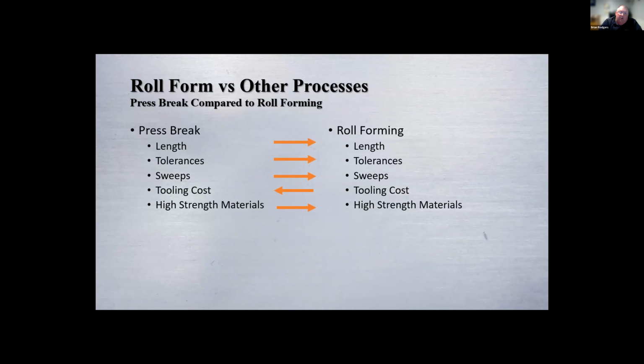Now, yes, there are press brakes out there now that will hit and hit until they get it exactly right. But you're losing cycle time, where in roll forming, you're just passing through the rolls and you're getting the same tolerance, but at a higher rate of speed. Sweeps, again, if you're making the profile, you're not putting a contour in the part. With roll forming, we're forming the profile and we have the ability to put the sweep in before the operator even touches the part. Tooling costs, as we all know, press brakes are pretty common, very inexpensive, but how many times do you have to do a tool change to get a part done, depending on what the profile is?